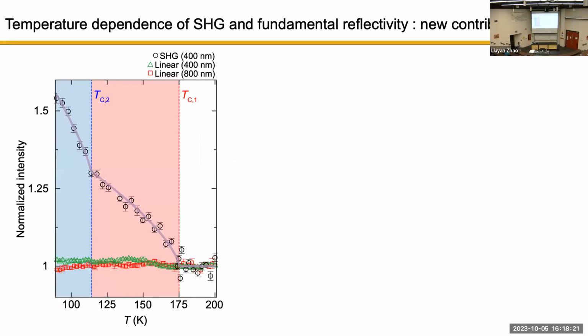So once we see the signal, we just choose one angle and then do a temperature dependent sweep. This circle is a second harmonic generation signal. You can see it's flat, then kicks up, and then another kick. So for the SHG, I do see 2 critical temperatures, one at 175, one at 120. In contrast, I do linear reflectivity, one at 400 nanometer, one at 800 nanometer. I see nothing, it's flat here. So this tells us that SHG is seeing something that linear optics cannot see.